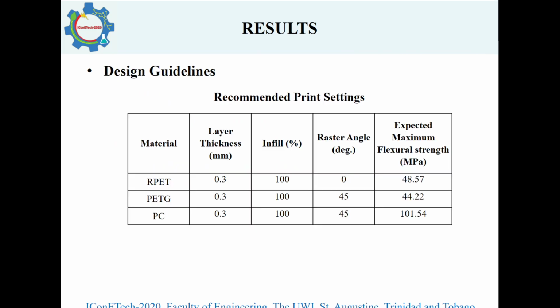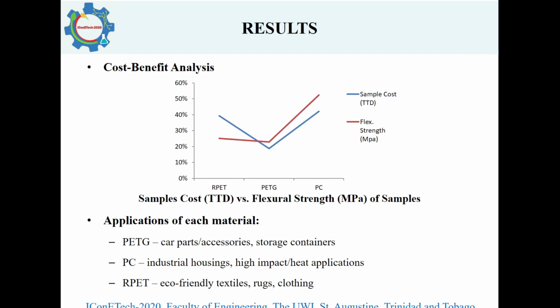Nonetheless, from the analysis, print settings for maximum achievable flexural strength can be recommended. As you can see in the table, in general, it seems that the larger the layer thickness and higher the infill percentage, the stronger the product, while the effect of the raster angle may vary with each material. Finally, a brief cost-benefit analysis was performed comparing the sample cost in Trinidad and Tobago dollars to the strength of the sample.